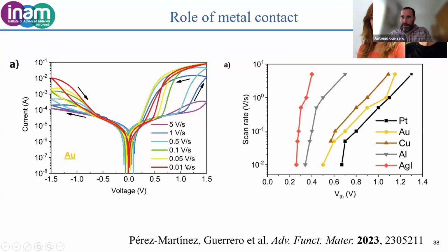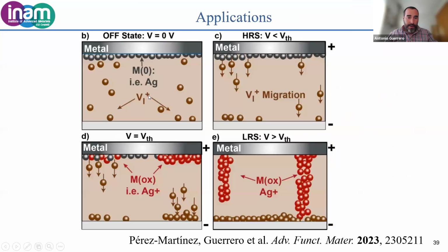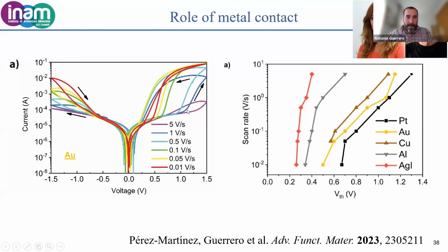But here we see that depending on the scan rate, there is a set voltage at which the device begins to activate. And this set voltage, we can plot for different metals, like platinum and gold, which are non-reactive, and metals which react a little bit. The kinetics are slow in comparison to aluminum and in comparison to silver. So we can plot this set voltage at which the current begins to increase very fast